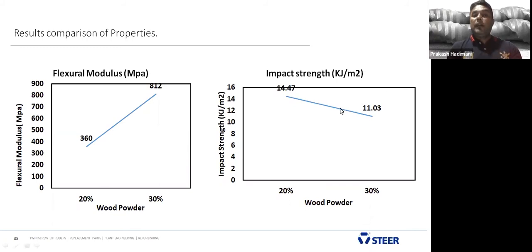Impact strength also reduces, because the viscosity goes higher and higher, and it reduces the impact strength. 20% is giving good impact strength. This is in kilojoules per meter square. With further addition of 10%, it reduces the impact strength.